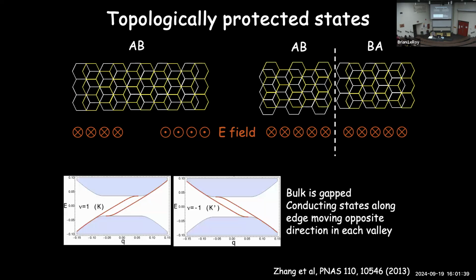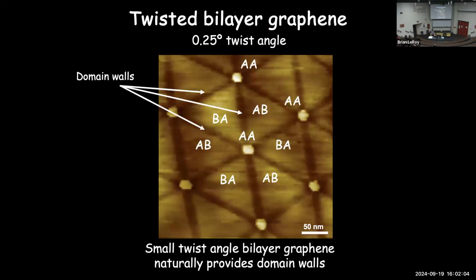And what that means is that along the domain boundary here, or along the 0 of the electric field, there should be conducting states which are going to be topologically protected in this system. So they're protected here and here. So we have the gap states, and then we have 2 topologically protected states which live along the edges of these graphene structures. And thankfully for us, this twisted bilayer graphene gives us that exact geometry that we need to observe these topological states. This is zoomed into the one I showed you earlier.